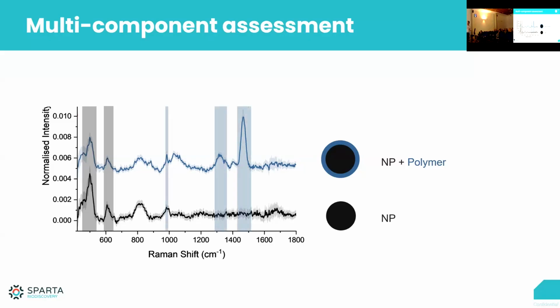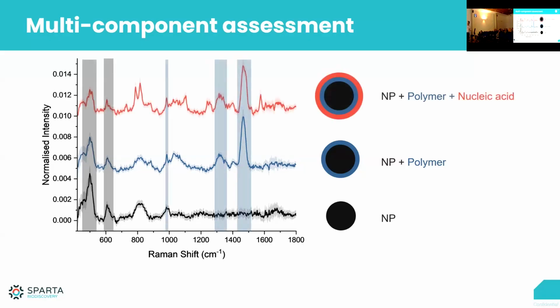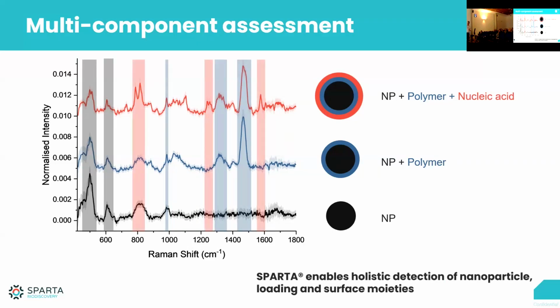And then we were adding here a nucleic acid as well on the surface. So you can see here, again, different peaks that were added clearly into this formulation, and we can look at the variability there. I think this was quite a good example to really see how a spectrum is built up. And it's quite important to have these controlled samples to be able to identify the different signals. It's not 100% necessary.